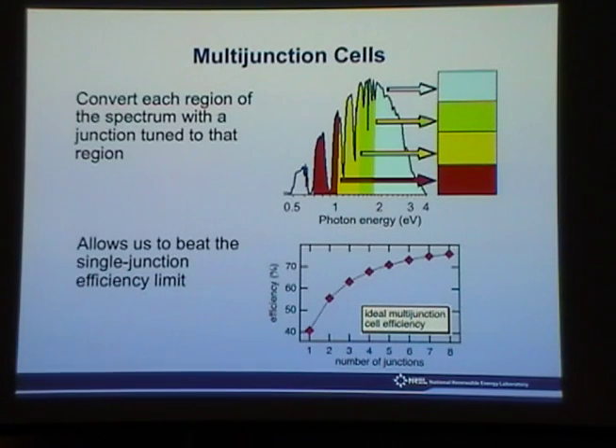So you could do it two ways. You can choose the band gaps such that for optically thick material, they are current matched. And that's sort of a mathematical algorithm of how to do that, right? So if you want a two-junction cell, you can find mathematically those two band gaps such that the total number of photons that each one absorbs are equivalent. But if you don't have exactly the right band gaps, then you can thin the material. Thin the material? You can thin the material, and I'll say more about that in a second.